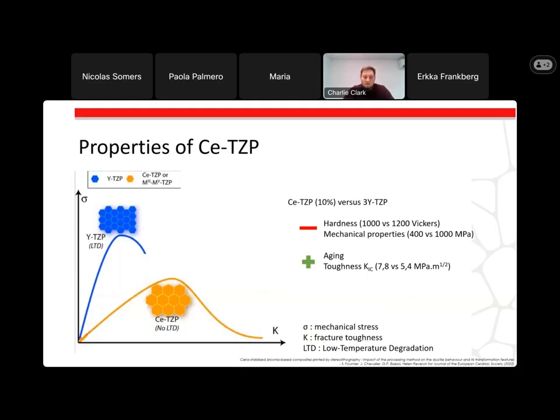So why we got told they chose the cerium stabilized zirconia over the yttrium was obviously the mechanical properties and the hardness was reduced, but the aging and the toughness were much better. But because we want to be able to use this in surgeries, mechanical properties still needed to be there. I think to begin with, the powder was supposed to be used in jaw reconstruction. So obviously you still need some mechanical strength.